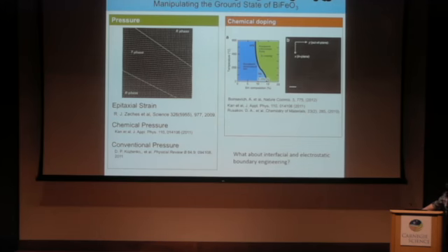With chemical doping, you can tune through a second morphotropic phase boundary, going from the standard R3c-like ferroelectric rhombohedral bismuth ferrite state. You dope in any rare earth, in this case samarium, and enter an intermediate regime with a 4-by ordering, like a lead zirconate-like, antiferroelectric-like structure. Then at high enough doping you transition into a paraelectric orthorhombic structure, similar to lanthanum ferrite or other rare earth ferrites.